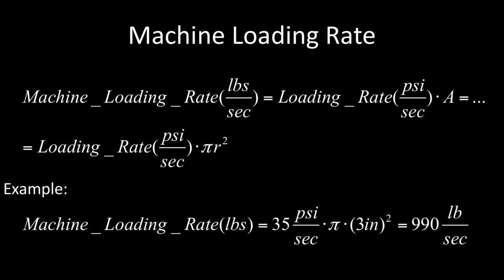The TA will ask you to compute the proper loading rate in pounds per second that the machine will have to apply in order to achieve the specified loading rate in terms of PSI per second. This is accomplished using the same procedures as was used to calculate the loading rate for the 4-inch by 8-inch specimens, the difference being the larger cross-sectional area of the 6-inch by 12-inch specimen.